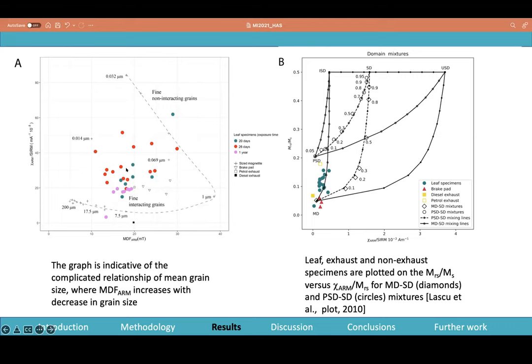And you can see that the leaf samples plot over a range of area over here. Then our brake pad samples plot over there, and the petrol exhaust plots over there in the finer interacting grain space. But one thing to note is that this particular plot is for sized magnetites, and if any of our iron oxide was surface oxidized magnetite, this should also be taken with caution, because this is not necessarily an exact representation of grain size distribution.